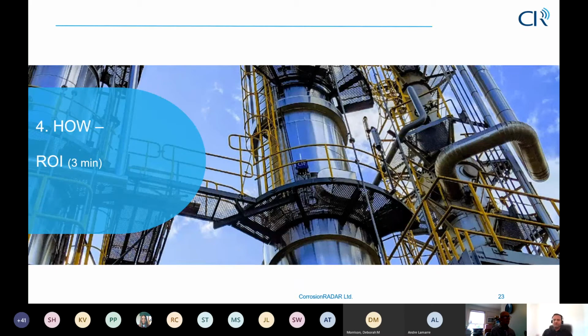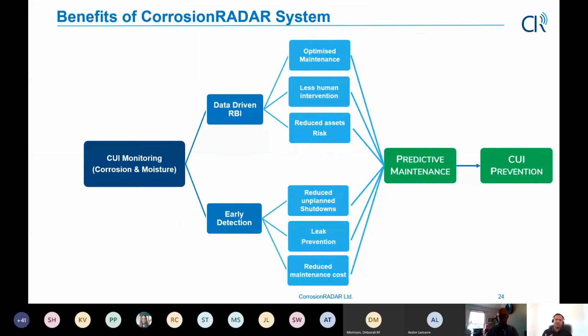So why should we do this? Because there is a return on investment, and normally we get involved with the end users to talk about return on investment. The benefit of the corrosion radar system is that the corrosion and moisture sensors, when working together, give you a data-driven RBI. Normally, RBI is a design-driven activity with very little field data on the real conditions of the asset. But in this case, you're getting direct data-driven RBI, where data such as the condition of the insulation and the moisture sensor indications get fed in, and that reduces the risk and optimizes the inspection procedures, leading to predictive maintenance and CUI prevention.